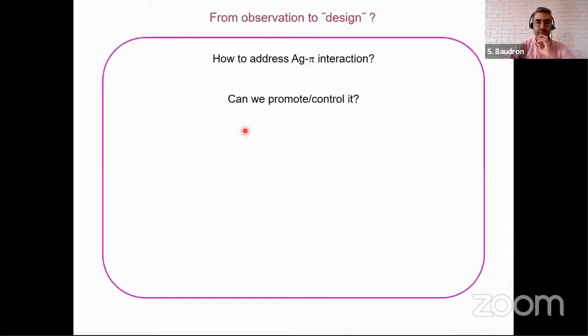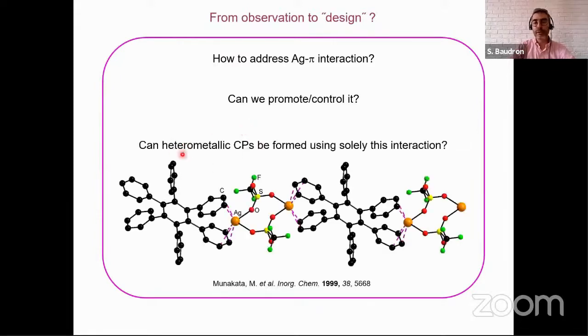So we went on to try to see whether we could address the silver pi interaction, and if we would be able to do so, whether we could promote or control it. In that case, one could hope to form heterometallic coordination polymers using solely this interaction, in analogy with what had been reported in the 90s by the group of Munakata, where they investigated polyaromatic systems and their assembly with silver 1 cations, such as the silver triflate salt, which forms a binuclear unit that is bridged by this hexaphenylbenzene.